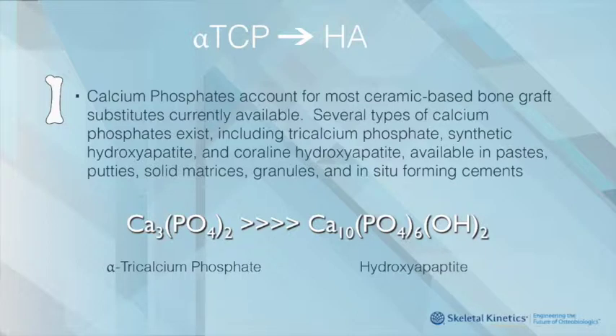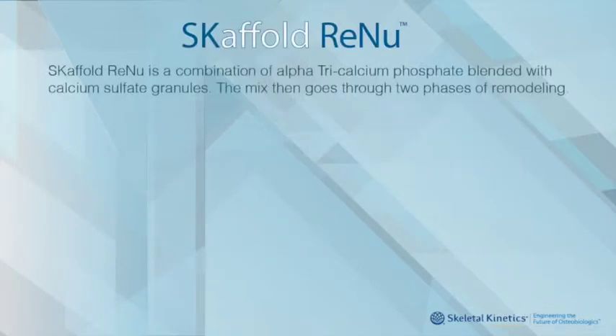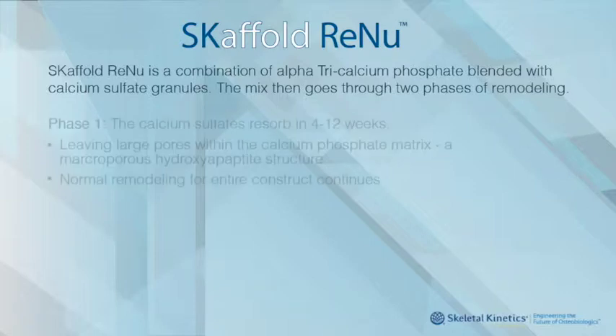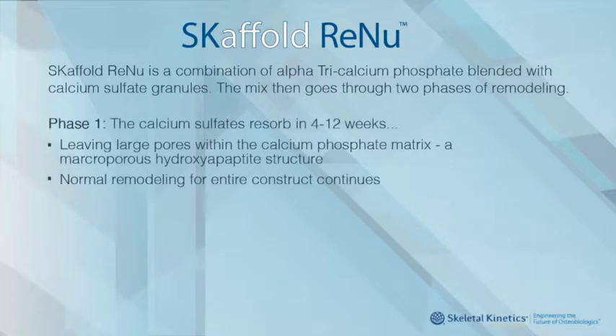To review, the alpha TCP will convert into hydroxyapatite. This is similar to the mineral phase of bone. Renu, being a combination graft of alpha TCP blended with calcium sulfate granules, creates a unique remodeling and resorbable graft. The first phase is the resorption phase, which occurs in the first 4 to 12 weeks. In this case, the sulfate will resorb, leaving large pores within a calcium phosphate matrix, which is, at this point, hydroxyapatite. Normal remodeling of the entire construct then continues into phase 2.